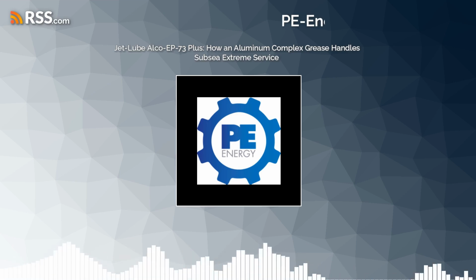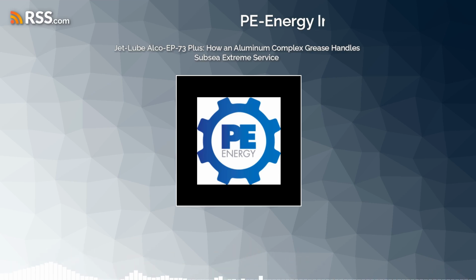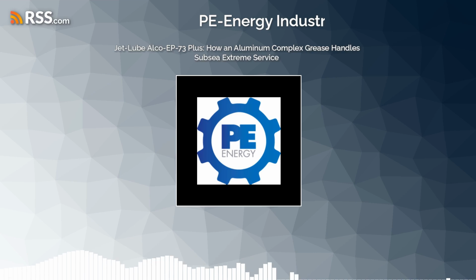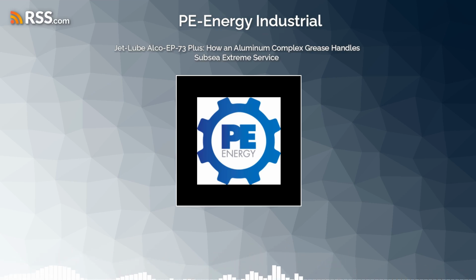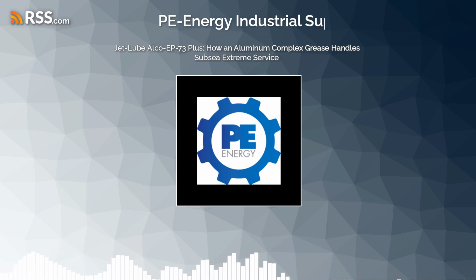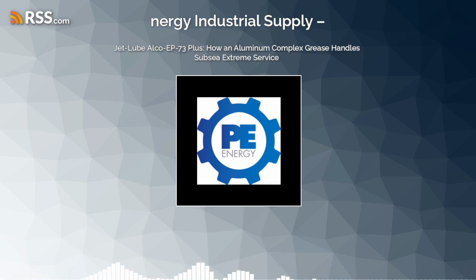A weld point of 315 kgf means they had to apply that immense concentrated crushing force before the additive force field finally collapsed. And then the metal superheats. Yes, the metal superheats from friction, and the 4 steel balls literally weld themselves into a single solid chunk. That is an astonishing amount of pressure resistance for something that is ultimately mostly oil and soap.